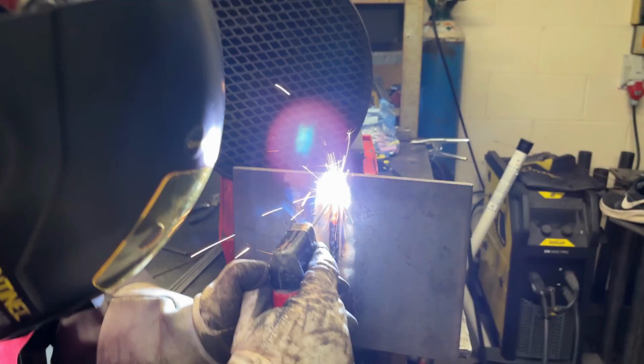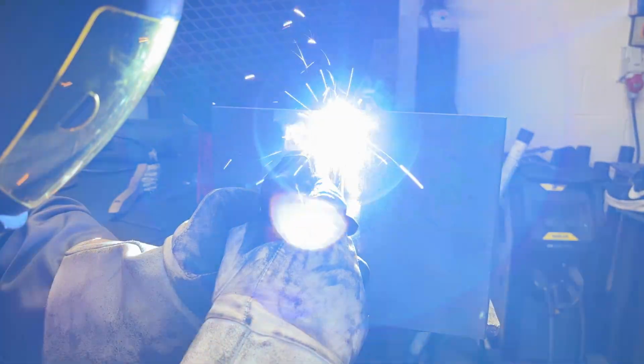With the root run in, we now switch over to 3.25 diameter electrodes and we're going to run them at 90 amps. At this stage we need to pay close attention to our heat input. If we put too much heat into the joint, the root run can remelt, which will force excess metal through to the back side. This can also cause two problems, either blowing through the material completely or sucking back the root, where the root run gets pulled back and leaves the joint weak.